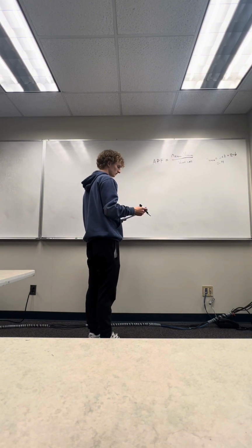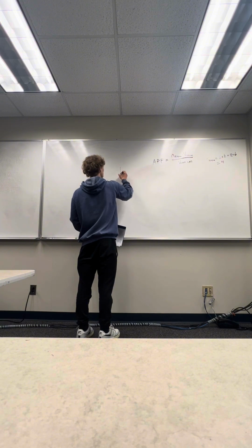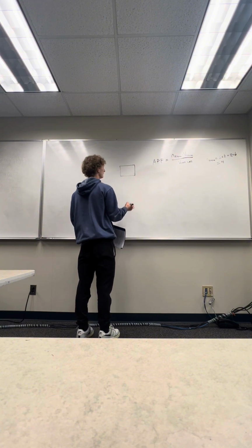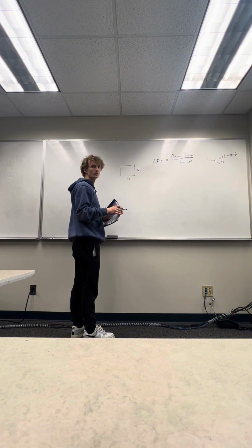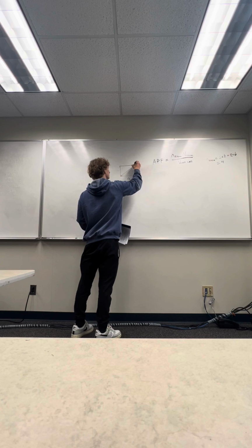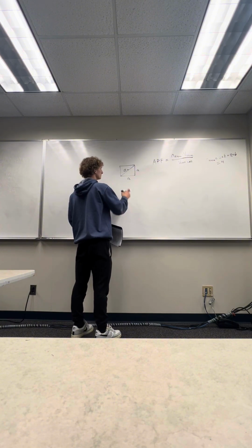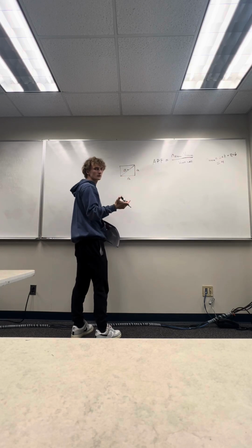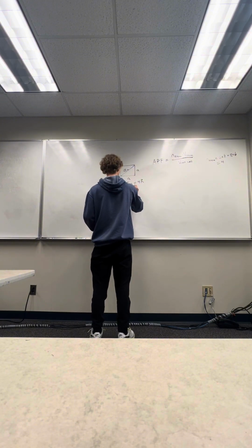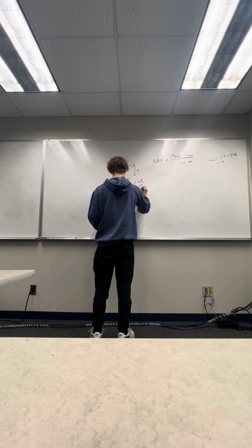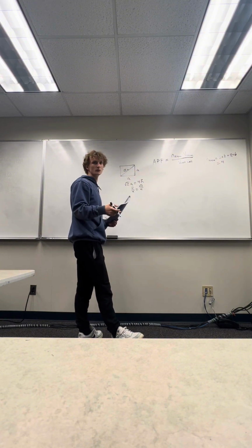And in order to find the volume of the unit cell, we have to take the front face of the cell, and the edge length of a unit cell is equal to a. And we have to find a relationship between a and r, the radius of the atoms. So we take the diagonal, which using the Pythagorean theorem is equal to the square root of 2 times a, which in an FCC structure, this diagonal has 4 radii. So you can set radical 2 a equal to 4r. And then r over a is equal to radical 2 over 4. And also the volume of an atom is equal to 4/3 pi r cubed because it's a sphere.